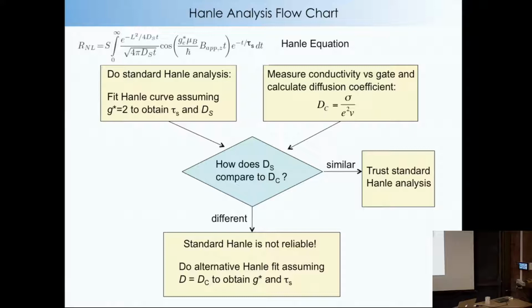So what you have to do is an alternate fitting. Instead of making D_s a fitting parameter, you take this value and put it into this formula, because that's independently determined. Then you do a fit to obtain the G star and the spin lifetime. That's the alternative way. This was developed by Van Wees himself, and we said, wow, that is very elegant, because in our original work it was a very complicated method. But this is very simple and nice.